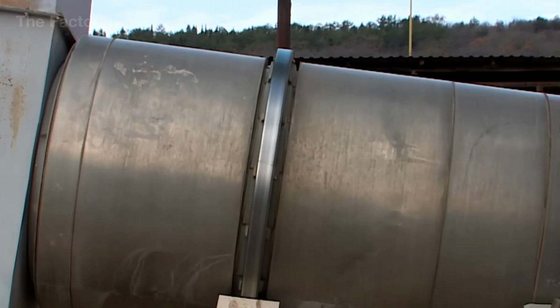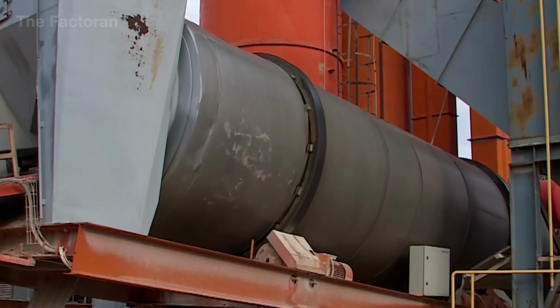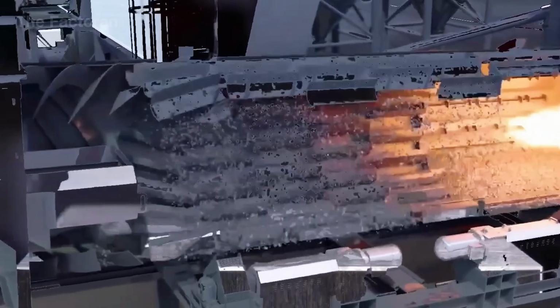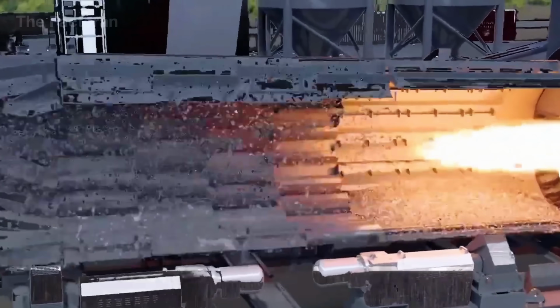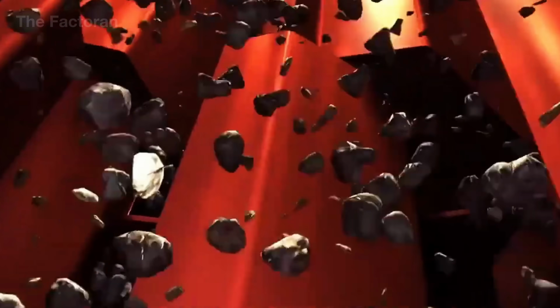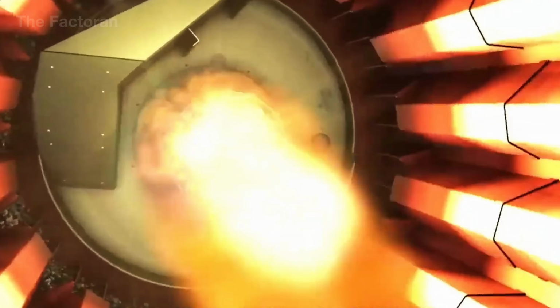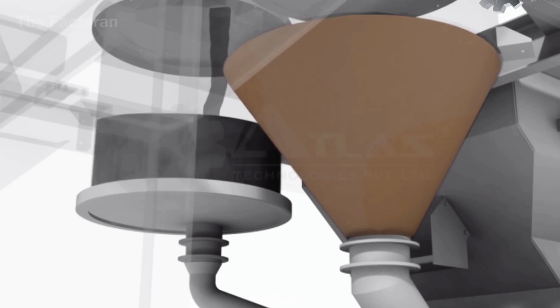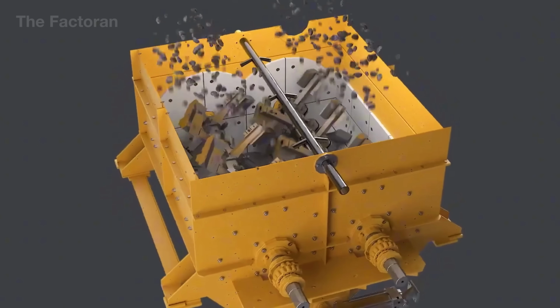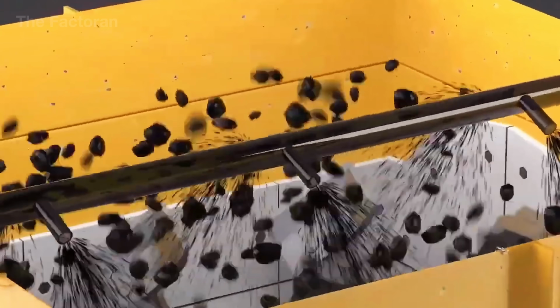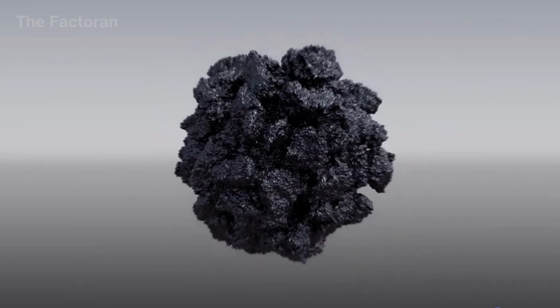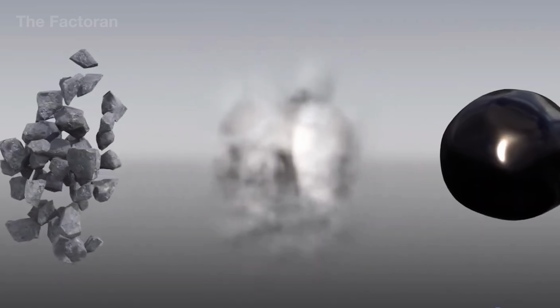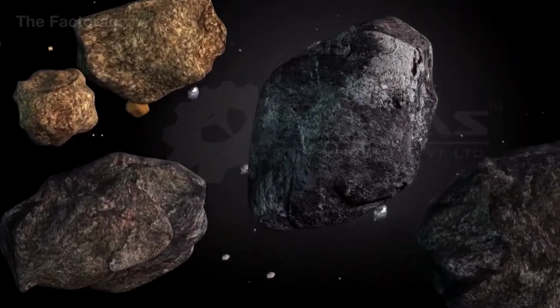Exiting the dryer, the hot aggregate is lifted into a multi-deck vibrating screen tower. Powerful vibrations classify the material by size. Large stones form the framework. Medium grains fill the gaps, and fine particles bind the entire structure together. Electronic weighing systems immediately measure each fraction, combining them according to a preset mixing formula. At the same time, the heavy oil fraction drawn from the bottom of the distillation tower, kept fluid by preheating to 300 to 320 degrees Fahrenheit, is pumped steadily through pipelines, ready to merge with the aggregate.